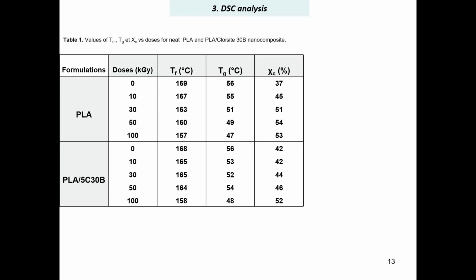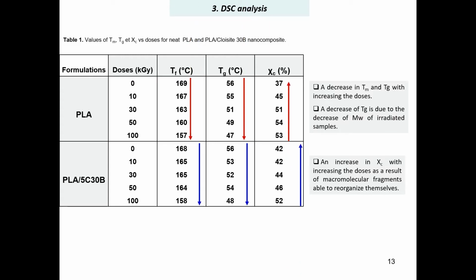The main thermal characteristics values of neat PLA and the PLA-based nanocomposites are summarized in table 1. And it is clearly observed from table 1 a decrease in melting temperature and glass transition temperature for both samples with increasing the doses. A decrease of the Tg is due to the decrease of molecular weight of irradiated samples. However, it is noticed that the decrease is more pronounced for the neat PLA when compared to the PLA-based nanocomposite. On the other hand, we notice an increase in crystalline percent with increasing the doses as a result of macromolecular fragments which are able to reorganize themselves.